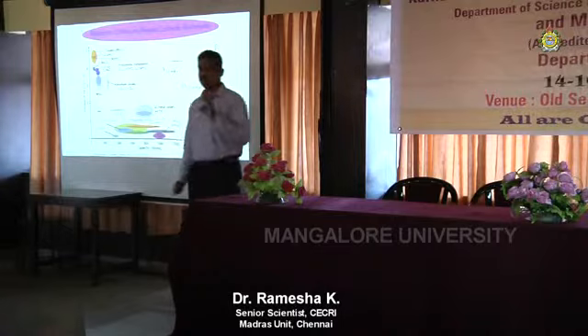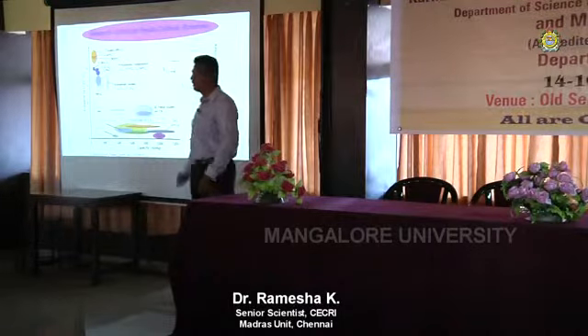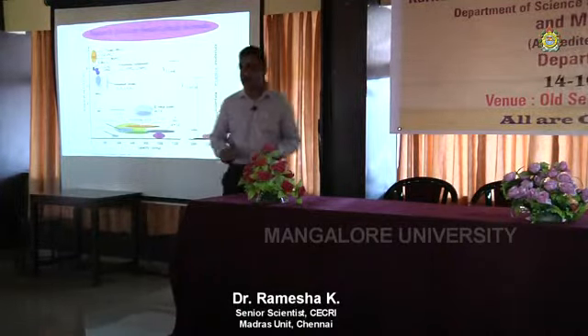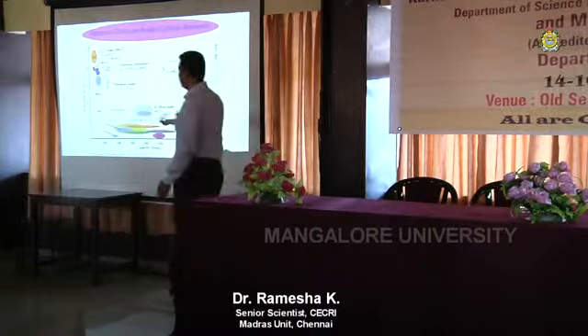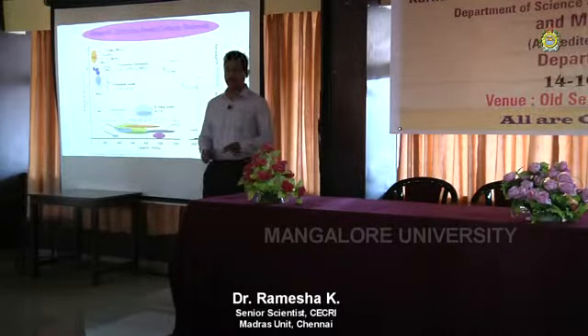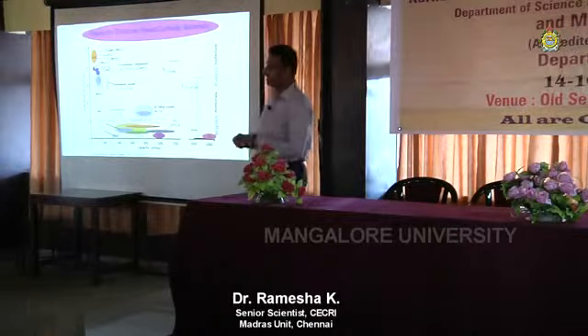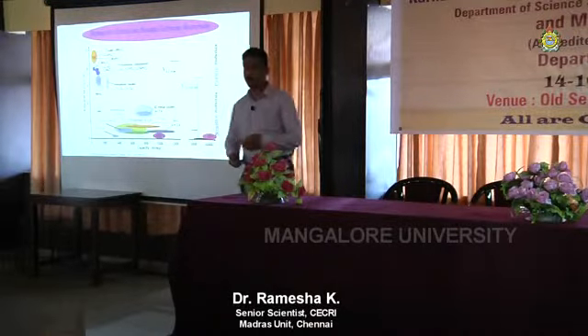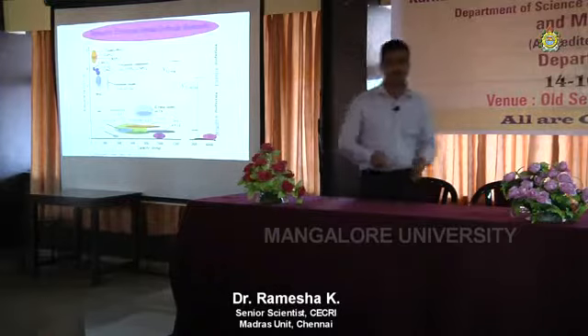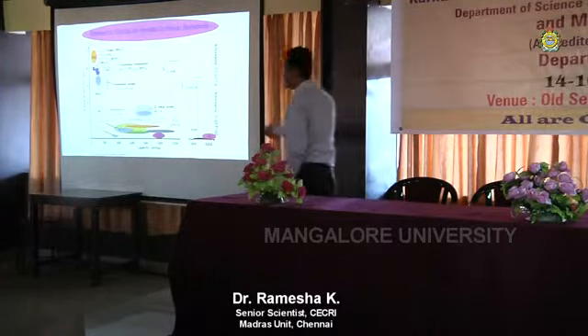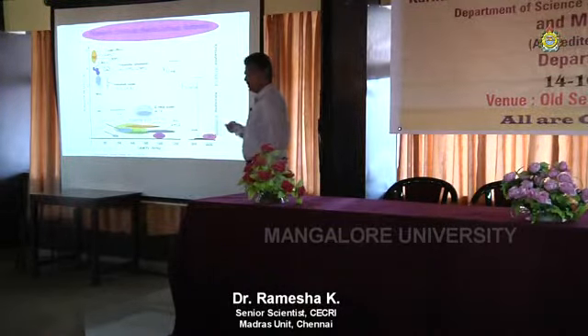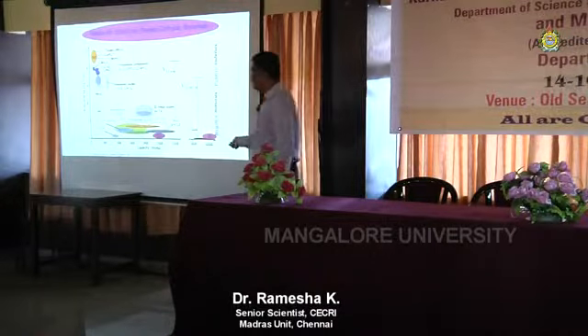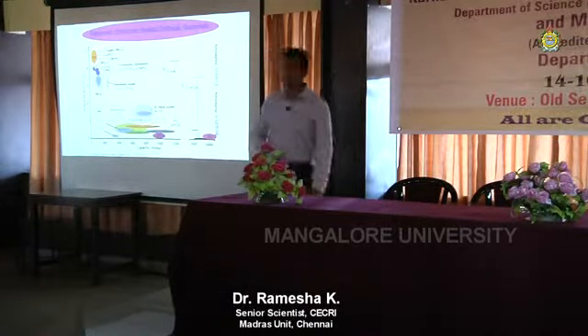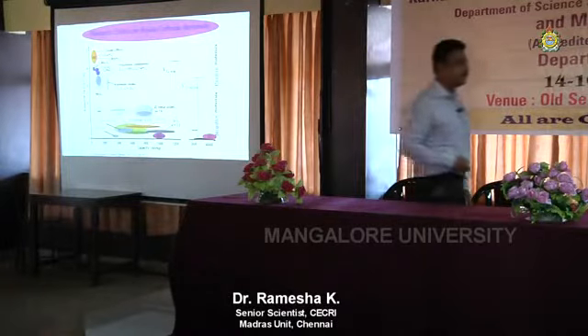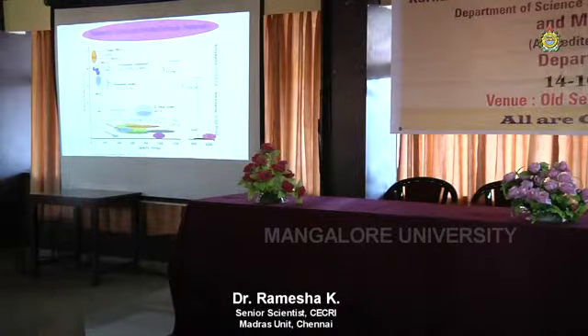In a battery, you need to have both with almost similar capacity. Otherwise, you cannot use silicon with a cathode like LiCoO2. Then there's a mismatch of capacity, and then you have the problem of how much material loading per square centimeter. All these engineering issues come. So ideally we need to move from here forward to this side. Well, the anode side is okay. The cathode is where we have a real problem. So in a lithium ion battery, the real problem is finding cathode material. Okay, next slide.